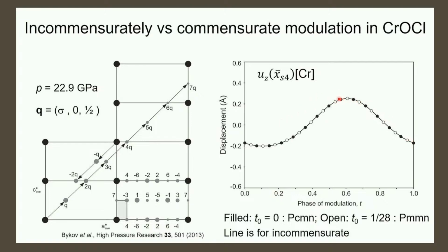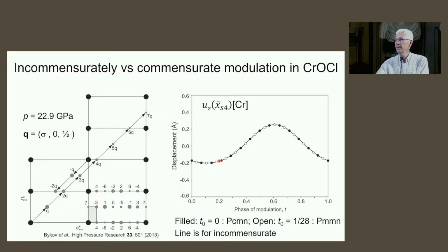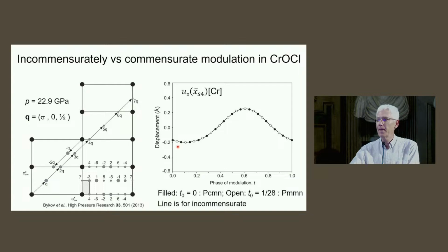We have a large displacement here, and a smaller or a negative displacement here, and 0 here. So that is all very similar, or one can even go as far here. If it's commensurate, it can be 0 or 1 over 28. But to move from 0 to 1 over 28, I don't need more than kT of energy. It doesn't make sense. There is no difference between the two. So eventually, the energy differences get too small to distinguish a high-order commensurate modulation from a true irrational or incommensurate modulation.